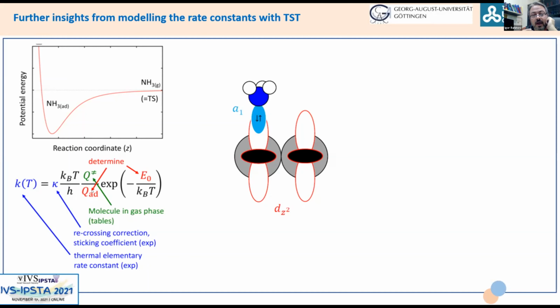So we also know from DFT calculations for the system that the degrees of freedom, such as frustrated rotation or hindered translation, which is a molecule-surface stretch, are closely coupled to the diffusion coordinate, to motion parallel to the surface. And therefore, in fact, we can only satisfactorily fit our data when we construct the adsorbate partition function such that it includes coupling of frustrated rotation and hindered translation to the diffusion coordinate.